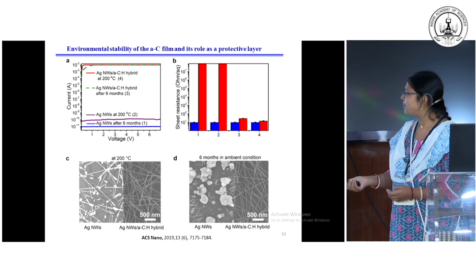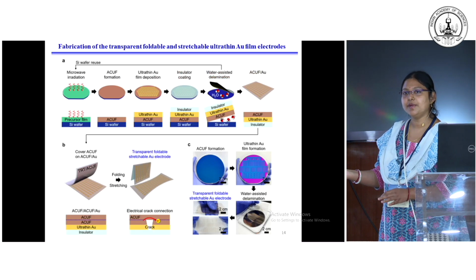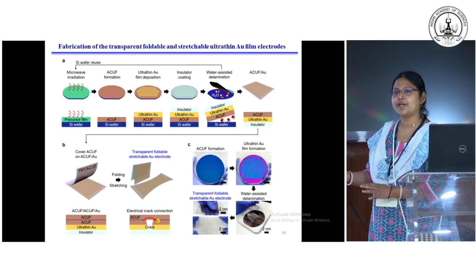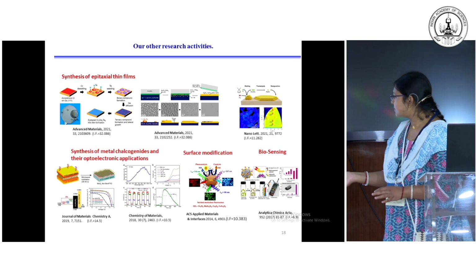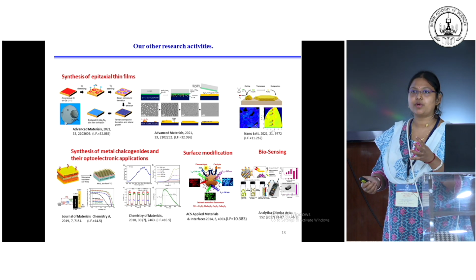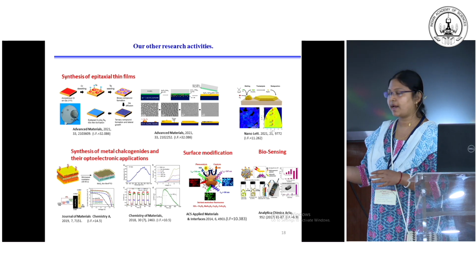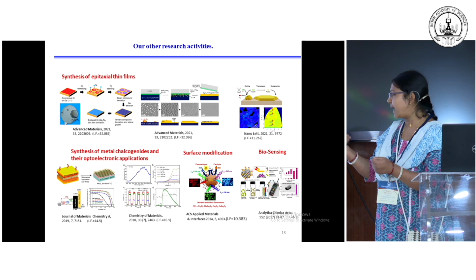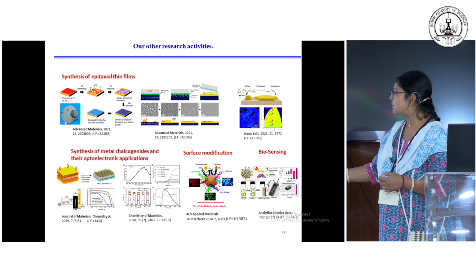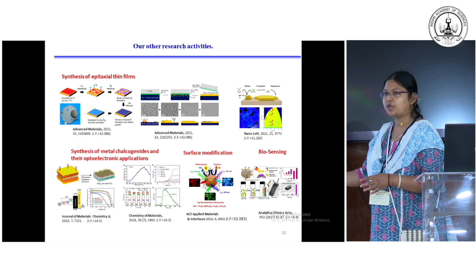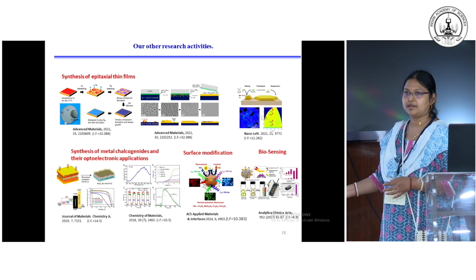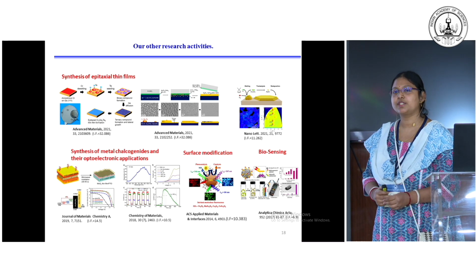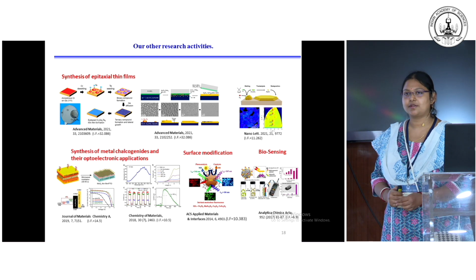And just one more. You mentioned that you have tried biosensing applications. Could you elaborate? Biosensing is different. That is not with amorphous carbon thin film. That is with oxide materials, iron oxide. I functionalized the surface of iron oxide nanoclusters, which are magnetically very responsive, with some half-fragmented antibody, and it was zinc doped. Zinc doping helped to attach the antibodies over the surface, and then we sensed the particular bacteria corresponding to this antibody. We detected the bacteria from milk using that antibody-functionalized iron oxide nanocluster. It's stable and very much reproducible.